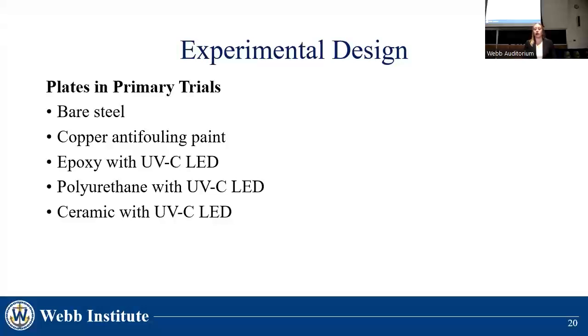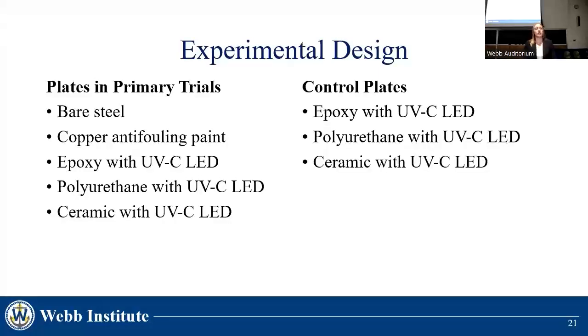Three different marine-grade coatings were chosen to test as light distribution mediums: epoxy, polyurethane, and ceramic. These coatings were chosen because they are designed for and used in the marine industry frequently, but all offer differing physical and chemical properties that may affect their light distribution capabilities. A copper anti-fouling paint was also included in our trials as an industry standard baseline, in addition to bare steel plates that would allow us to observe unimpeded biofouling growth. In addition to these primary trials, a second set of coated plates were constructed to be a control group to test coating degradation from UVC exposure over a longer period of time.